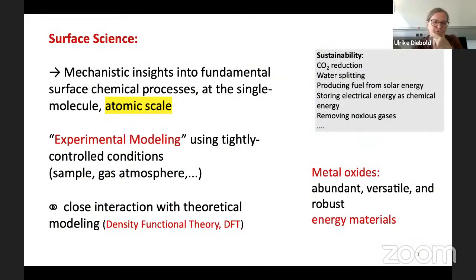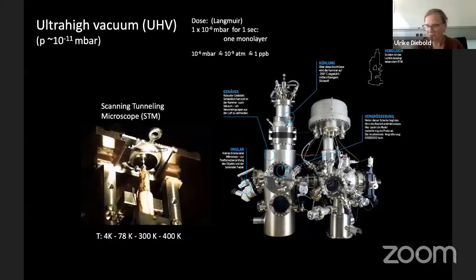When I say controlled conditions, what I mean is that, when we do classical surface science, we conduct our experiments in one of these ultra high vacuum chambers, where underneath here there are some pumps. We do this at a pressure of 10⁻¹¹ millibar, so very far away from what real electrochemists do. Not only dry instead of wet, but also very low pressure rather than ambient pressure.